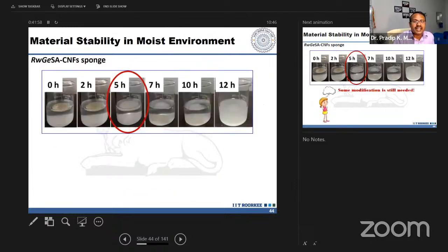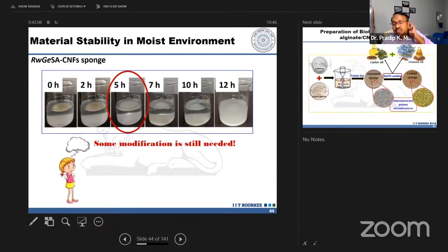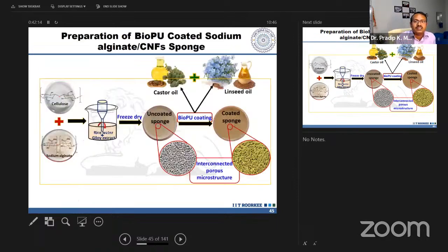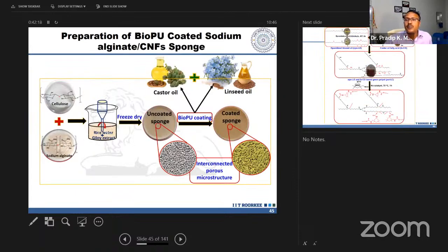We must think about what happens after 5 hours in water media: it is going to almost dissolve. So some modification is still needed to make it mechanically stable for application. So we have done a very interesting thing: we developed a biopolyurethane coating on this material, so that the material property enhances without deteriorating its microstructure and its antibacterial property. All the things remain the same, only mechanical property and solution stability showed very good improvement.